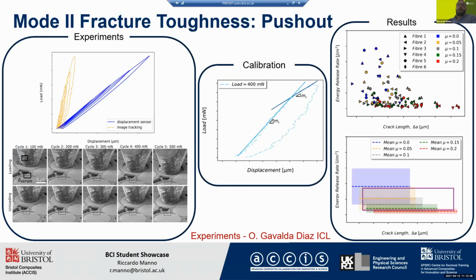For what concerns mode 2 fracture toughness and frictional stresses, we use the unloading-loading push-out test coupled with a VCCT analysis at different levels of Coulomb friction coefficient. This method allows us to calibrate the crack length upon just stiffness response comparisons, and therefore find the range of allowed critical energy release rates and frictional coefficients.